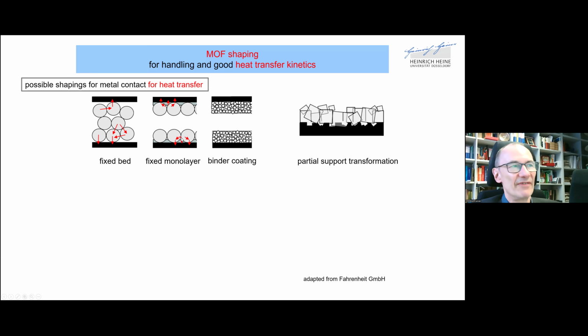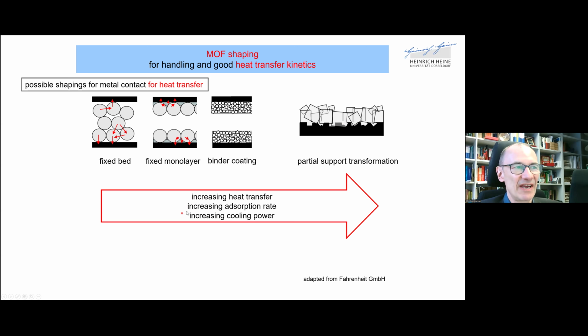So if you glue the spheres onto the metal surface, this heat dissipation is a little bit more effective. And if you make the spheres smaller, let's say into nanoparticles, then you can make this heat dissipation even more effective by having a more intimate contact with the metal surface. And the best would be if you transform the metal surface partially into your metal-containing porous material. Because this way, you have a direct contact, because this metal coordination network or MOF will be grown directly from the metal surface. So from left to right, you have an increasing heat transfer. That means an increasing adsorption rate and an increasing cooling power.